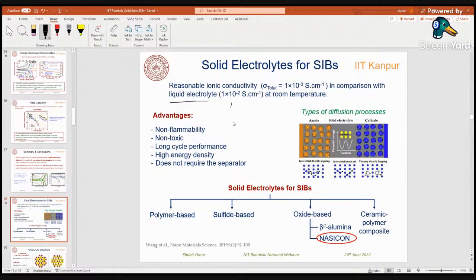Now the highest conductivity that we can obtain from the solid electrolyte is around 1 millisiemens per centimeter. So there is a gap of one order of magnitude between the solid electrolyte and the liquid electrolyte. Okay. Now, what are the advantages of the solid electrolyte?